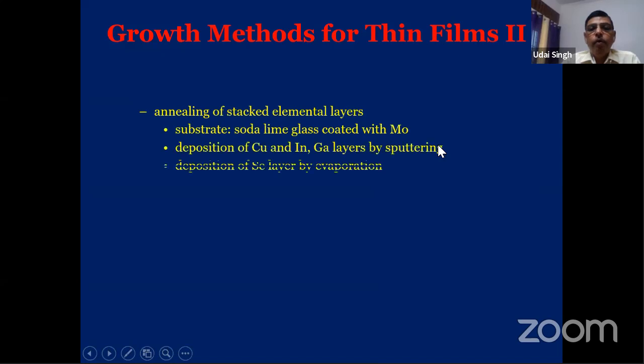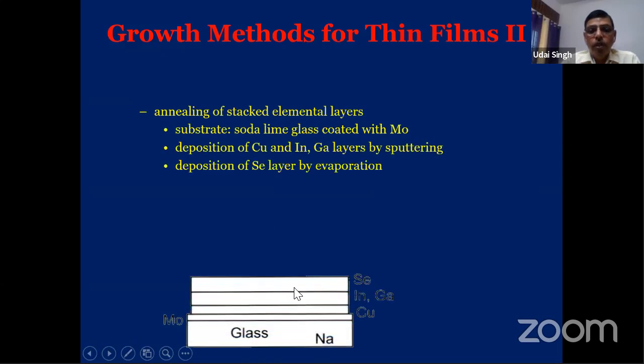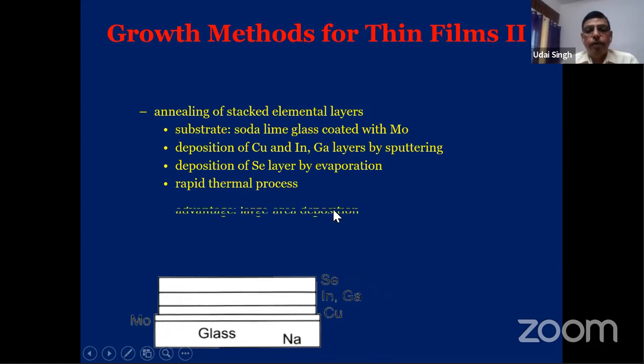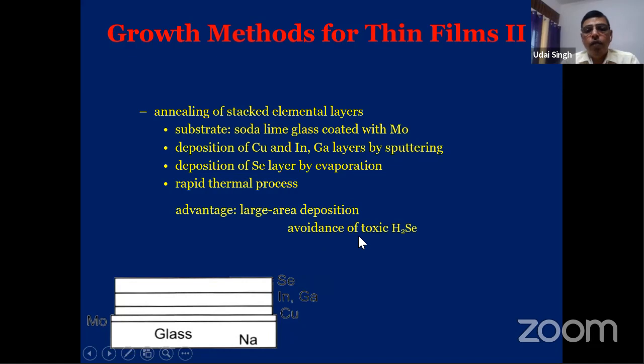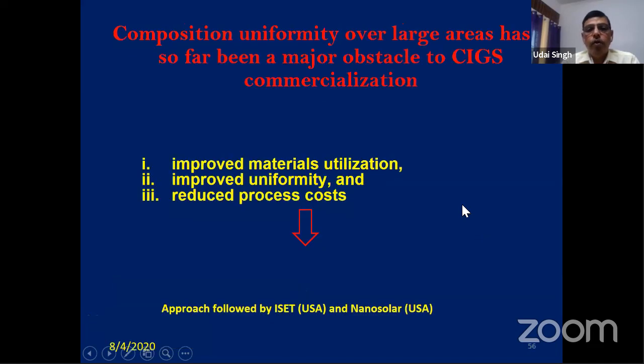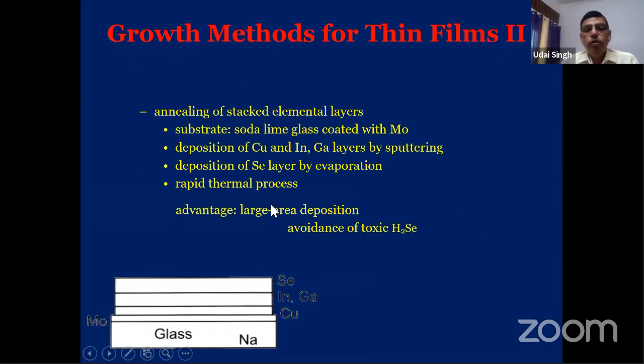So people have tried to replace this with selenium. Same process there. What happens is they deposit the selenium on top of this. They are not using hydrogen selenide gas to avoid the toxicity. So they deposit a selenium layer by evaporation, and then they use rapid thermal process for annealing. So large area, avoidance of toxic H2Se, and you get a good compound. So this is the second method.